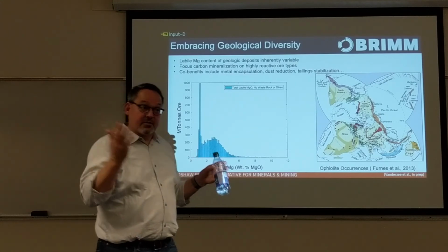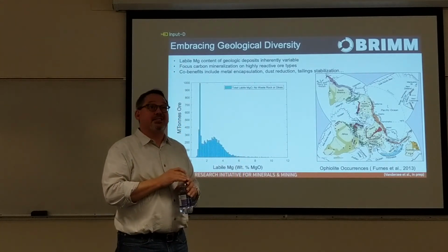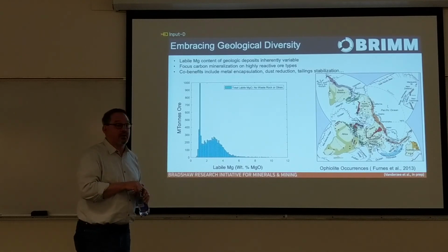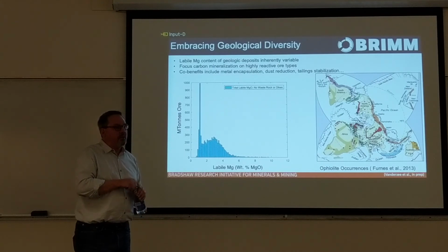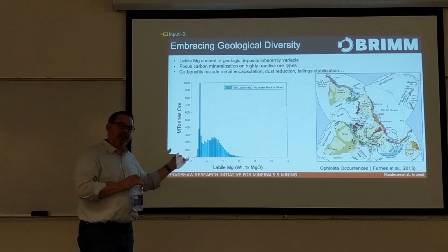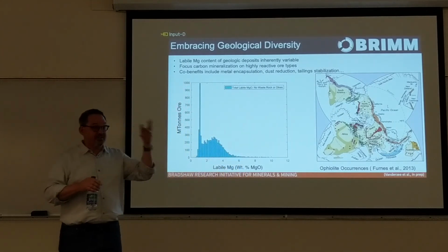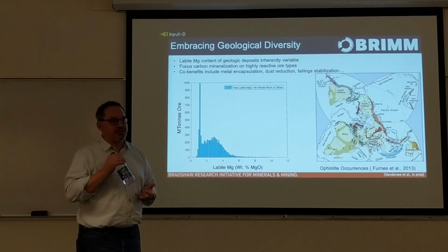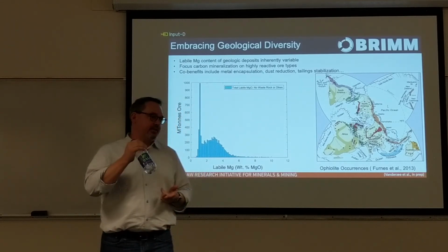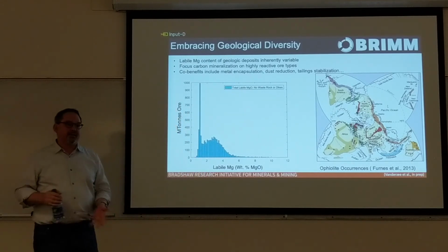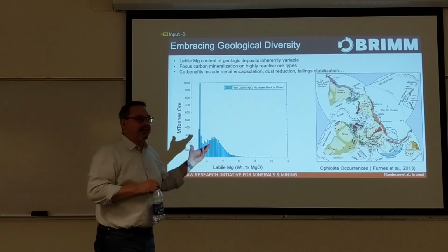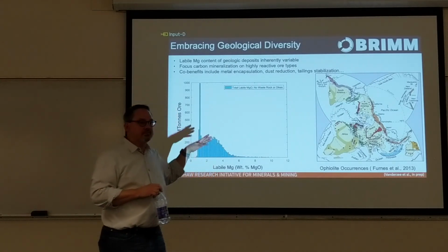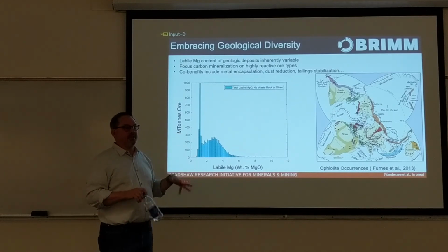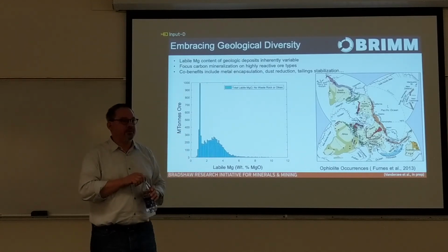There are some people who have looked at smectites and things like that for cation exchange for carbon sequestration. Nobody's really had a eureka moment. But up until the tailings work, everyone talked about mineral carbonation as something you do with olivine. Olivine's the most reactive, and you get 80% reaction in 20 minutes by going to 220 degrees, 200 bars, and it's a $200 per ton process. This approach gives up on all of that reactivity. We get our reactivity through volume, not through efficiency.